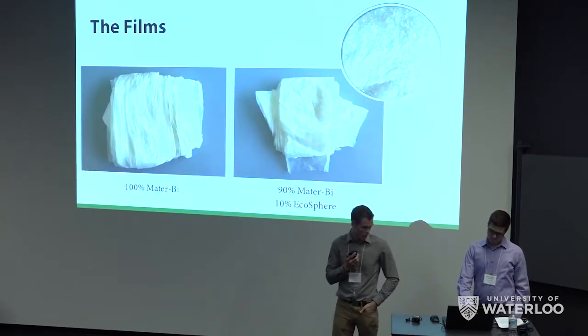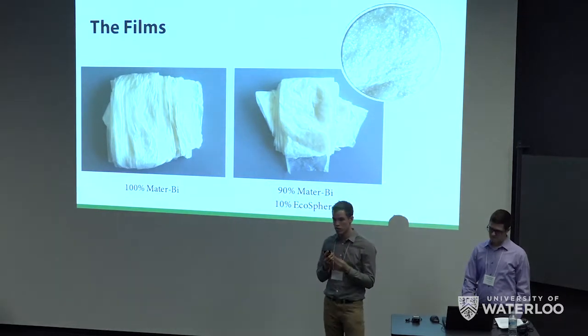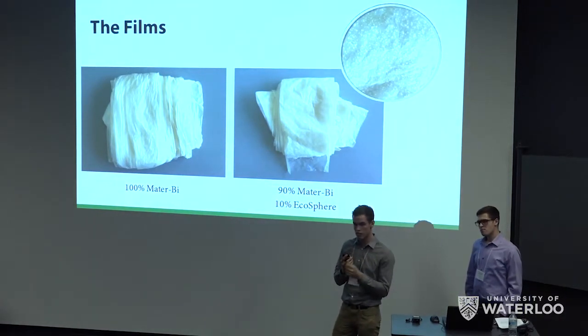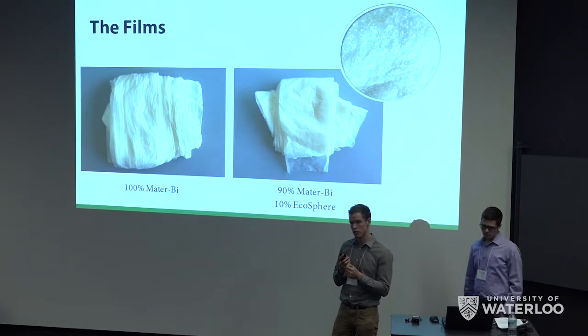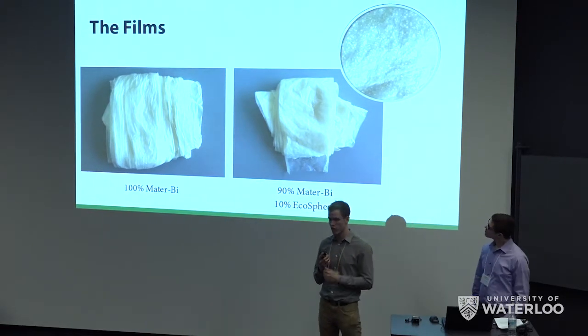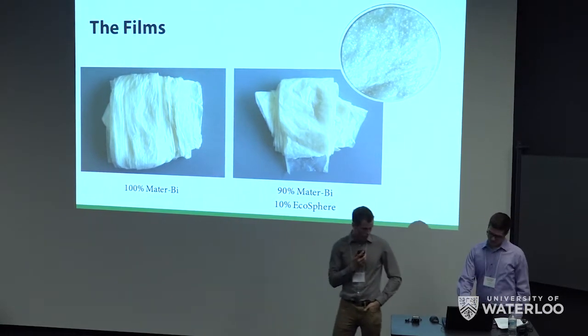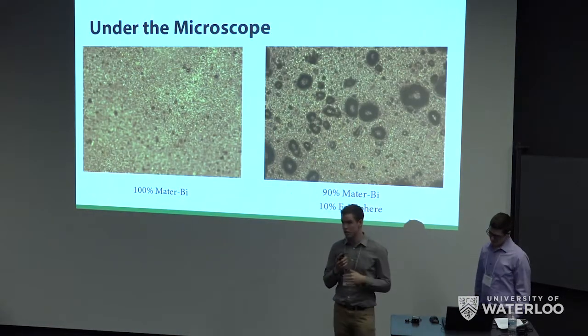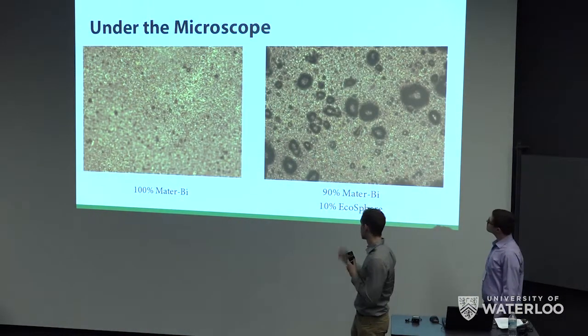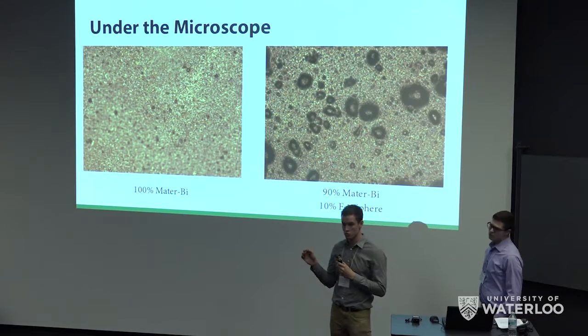So after this, we brought it back. If you look at your samples, you can see that one is very smooth, where the other one has these well-distributed clumps in it. So those clumps are aggregates of our nanoparticle. So looking at them under a microscope, we could visibly see much better that the EcoSphere is still aggregated into particles.